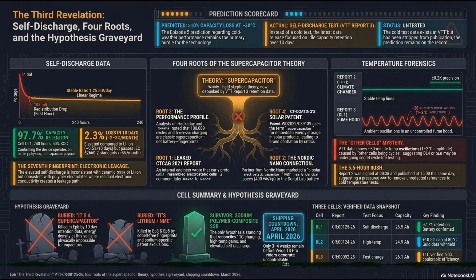Exactly. Now, the second factor dragging down the energy retention is the 10-day rest period itself. Because over the course of those 240 idle hours, the internal voltage of the cell slowly sagged by 128 millivolts. And when VTT finally commanded the cell to discharge the remaining 97.7% of its capacity, every single one of those remaining electrons was delivered at a lower average voltage than it would have been if they had discharged the cell immediately. So the capacity, the raw count of electrons, is still sitting in the cell, but the pressure behind those electrons has weakened after sitting for 10 days.